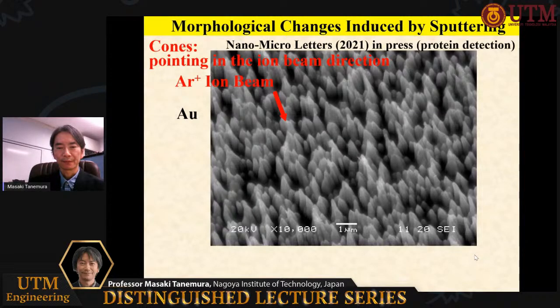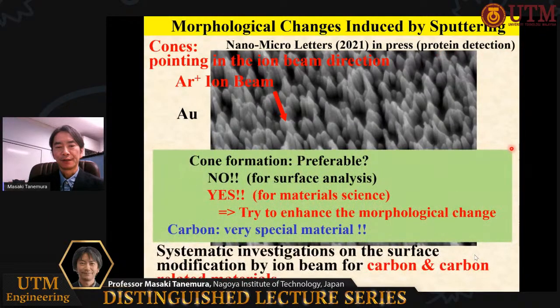This is a typical example of the morphological change induced by ion irradiation. You see the conical structures. They are pointing in the ion incidence direction. These are conical structures formed on a gold surface to detect protein. From the viewpoint of surface analysis, the formation of conical structures should be avoided for precise analysis. But for materials science, it is very interesting, and we tried to enhance the morphological change as much as possible. In this systematic investigation, we found that carbon is a very special material.